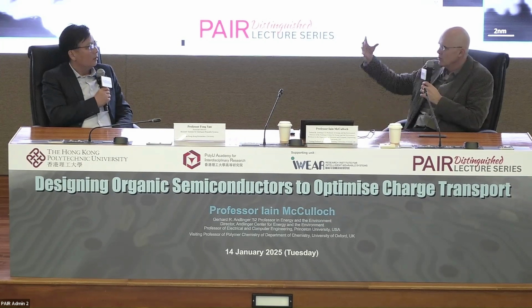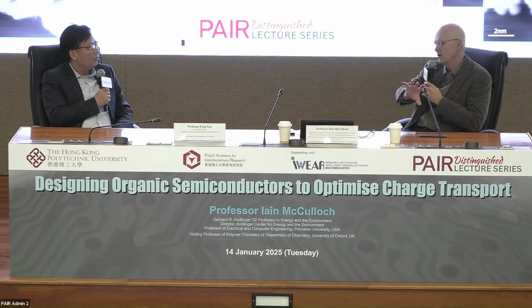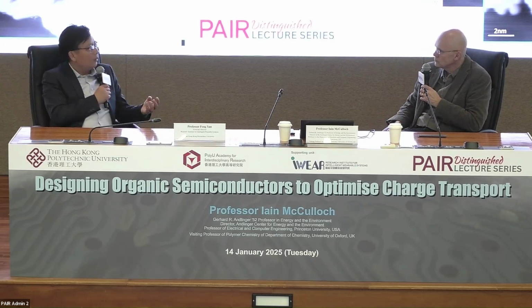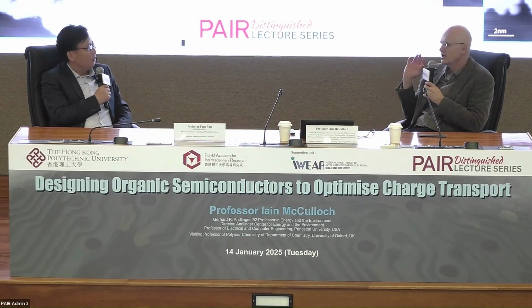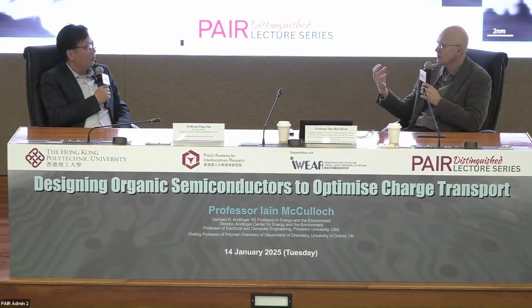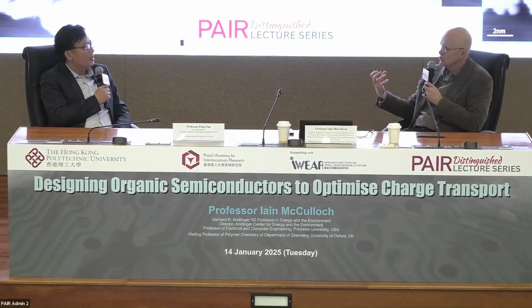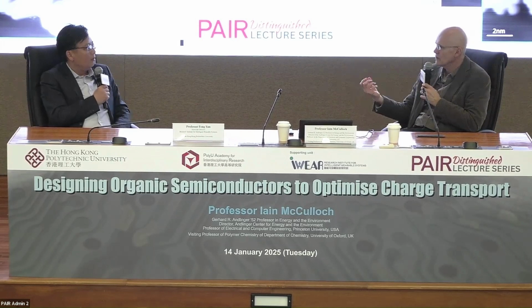That's basically what we're trying to do now, to try to introduce aqueous channels outside of the electronic channels to separate them. At the moment, your ions just come right in and compensate the polarons, increase the effective mass, and increase disorder and disruption around the material. Now, our design strategies that we're thinking about are ones where you have a charge transport channel and an ionic channel separate. I think that way you have hopefully no swelling. That could be a mixed ionic electronic conductor, but instead of the mixed nature interacting, in this case, it's slightly separated. So you don't have the negative consequences of ions.